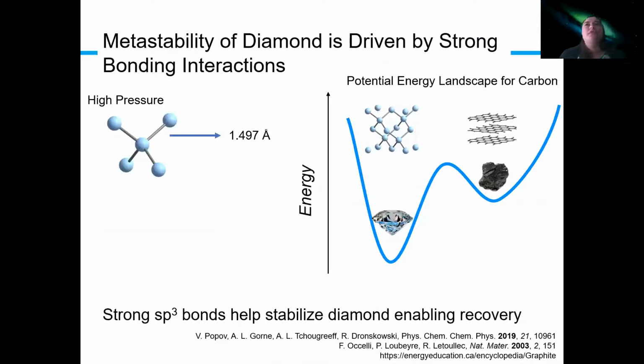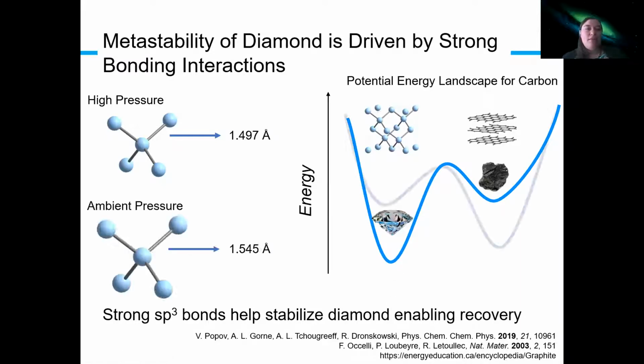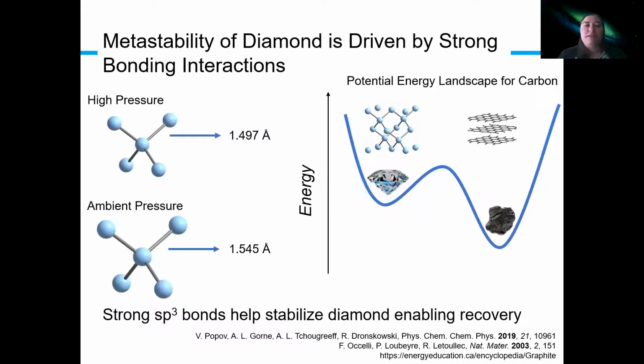But one of the challenges is what materials are stable down to ambient conditions. And perhaps a classic example of a high pressure material that is recoverable to ambient conditions is diamond. And diamond is thermodynamically stable at higher pressure in that it sits at the bottom of this potential energy well here. But at ambient pressure, it actually is metastable, meaning it's not sitting in a global minimum, it's sitting in a local minimum. And one of the things that I'm really interested in is why is this material stable? And part of the reason is that it has these sp3 bonds that help stabilize the structure upon decompression.